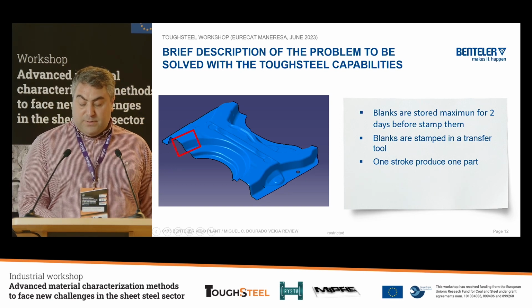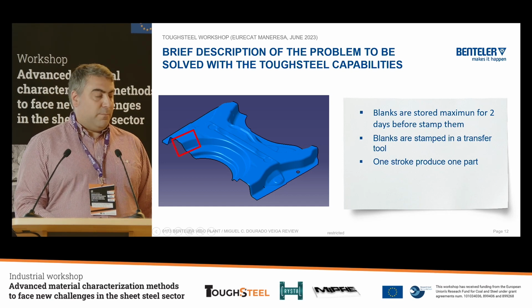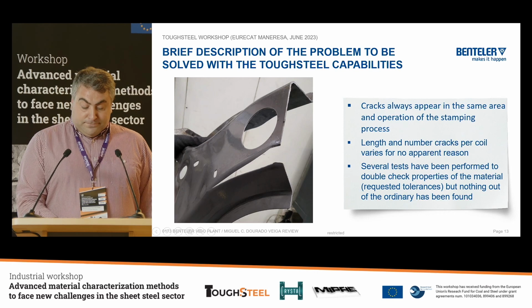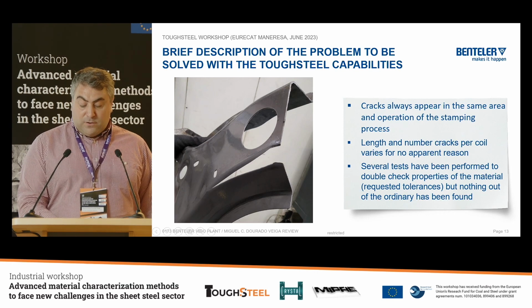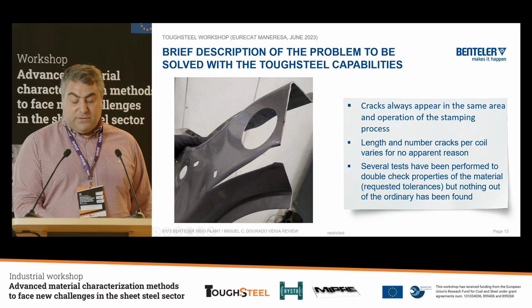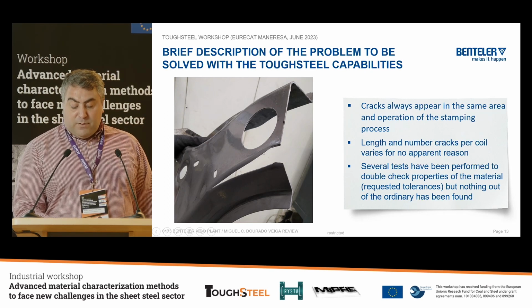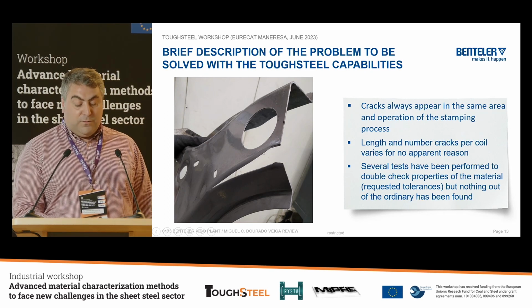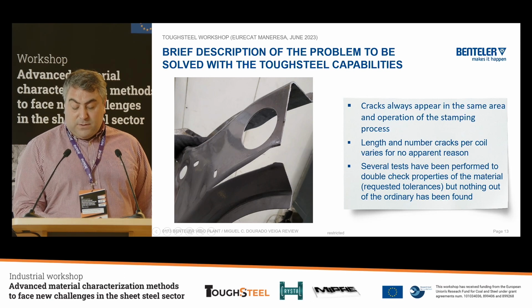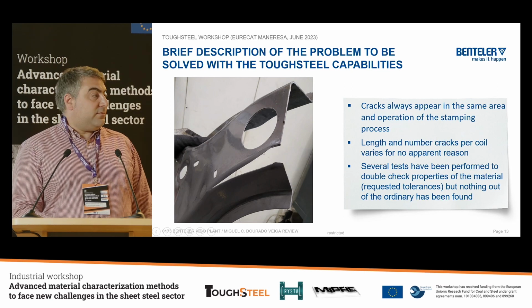Blanks are stamped in a transfer tool, and one stroke produces 1 part in the stamping process. The cracks always appear in the same area and operation of the stamping process. The length and number of cracks per coil varies for no apparent reason, and several tests have been performed to double-check the properties of the material, I mean our requested tolerances, but nothing out of the ordinary has been found.